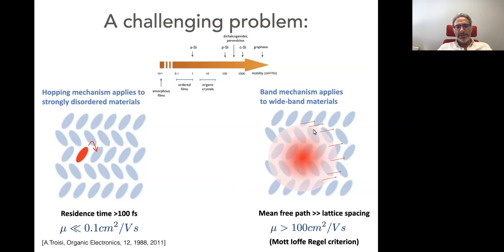To apply band theory, you need mean free paths that are larger than the lattice spacing, because you start from a wave description of the carriers, and you can't define waves if the mean free path is shorter than the lattice spacing. Typically, setting the mean free path to one lattice spacing gives you mobilities right at the values that you encounter in organic crystals.